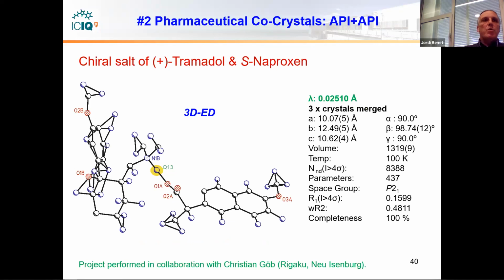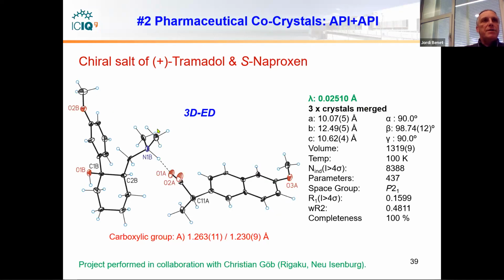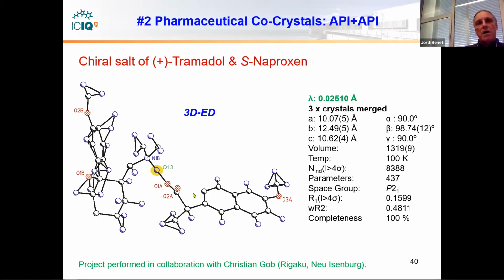And we could then do a test. We took this structure, deleted all the hydrogen atoms, and just refined the structure without hydrogen atoms. As you can see here, all the Fourier peaks, all the remaining electron densities which appear, corresponded to the positions of the hydrogen atoms, including the hydrogen atom of the hydrogen bond. So it's clear that using electron diffraction, you can better localize hydrogen atoms than using X-ray diffraction.